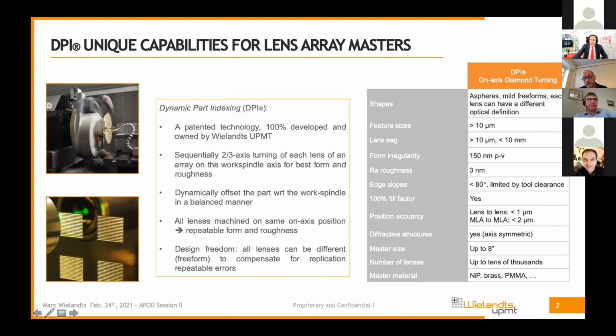It's a patented technology. It allows us to machine very efficiently and very accurately masters or lens arrays in metals or in PMMA in a single process without ever stopping the process. And this with positioning accuracies of a micron over an 8-inch wafer, and also form accuracies like you can obtain from turning. So a few, let's say 100 nanometer, 150 nanometer PV on these surfaces.